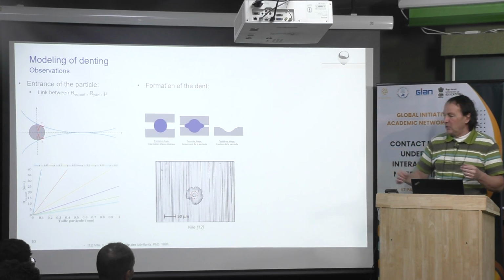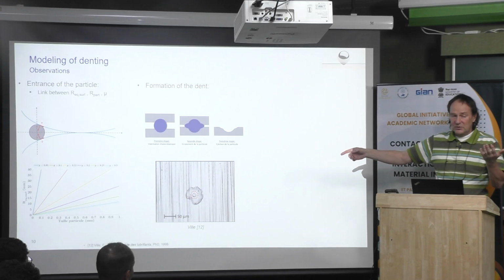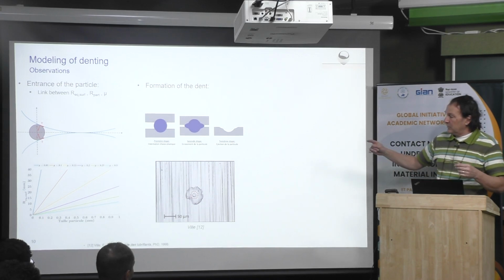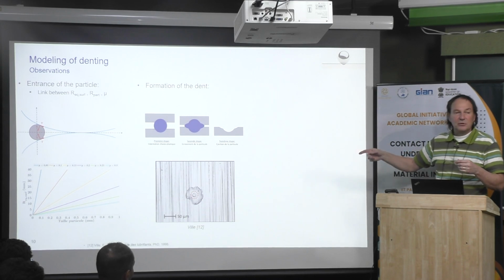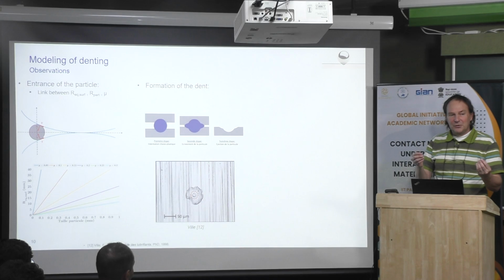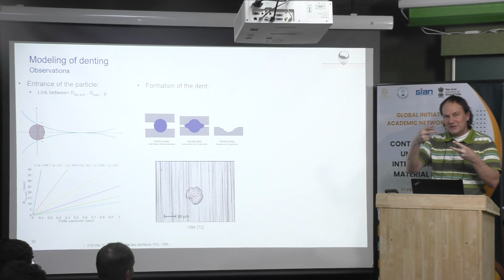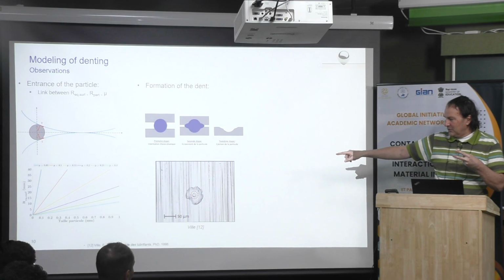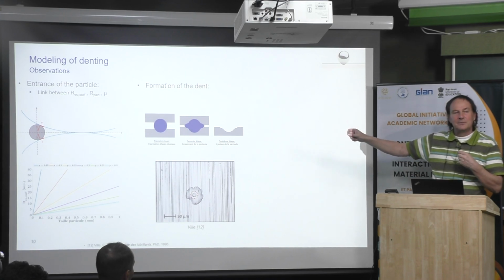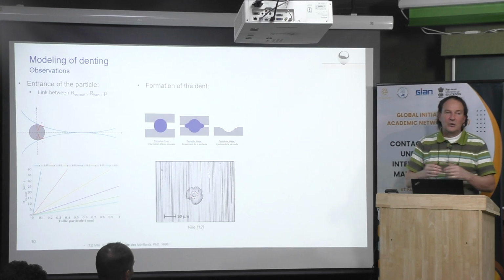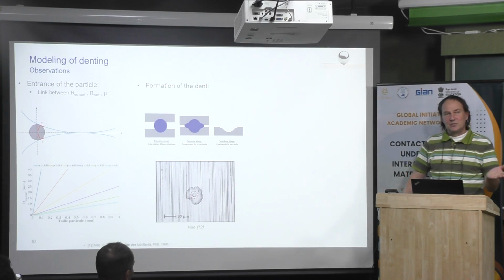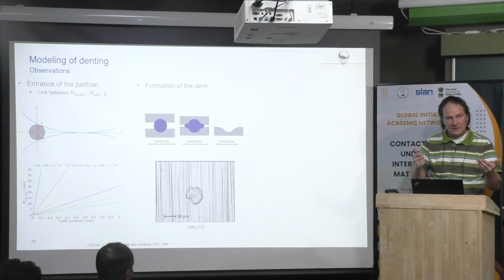Then very often what we do, we dent one of the discs like that, or also it can be done with artificial indent. We make a few cycles of operation, for example, 1 minute, 10 minutes, up. We stop, we dismount the dented disc, and we use only 2 smooth discs. But one of the smooth discs will have been submitted to very high pressure, and it will fail very quickly. It's difficult to see, but sometimes you can see a mark on the other disc. This is what we call the boomerang effect. There is no dent, but the dent will mark the other disc when the dent is very important.